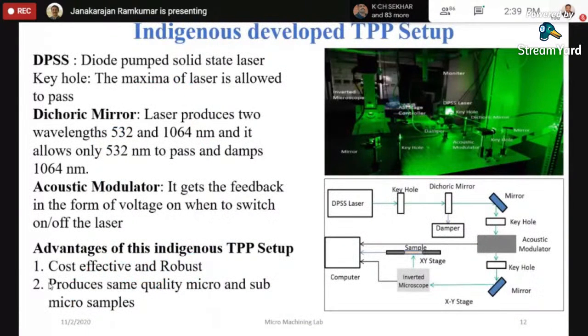What we developed in our lab was an indigenous 2-photon setup. What we did was we effectively used a microscope. And why did we use a microscope? Because if we put a mask and allow the laser to pass through the mask, we could have a magnification or a demagnification, so it will focus or defocus on a spot. If we just use the 10x, 100x, whatever is given to the optical microscope objective, we could develop a small setup. Our setup is not working for nano texturing, but we could do a lot of micro texturing, through which we published a lot of papers.